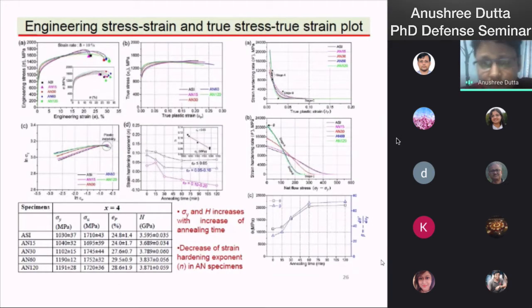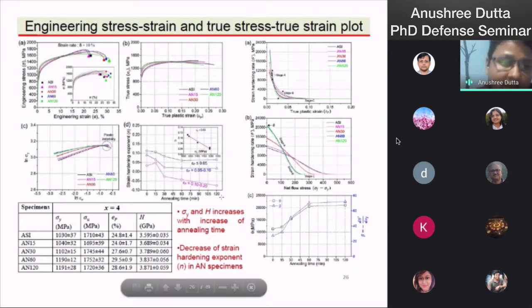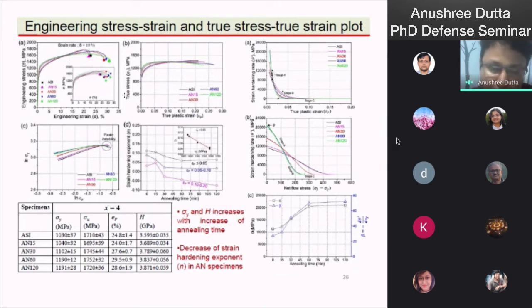The engineering stress strain plot shows that the annealed sample exhibited improved yield strength after annealing, and the true stress strain diagram shows the improvement of strength after annealing. The true stress strain diagram is plotted in log scale to estimate the strain hardening exponent, and the strain hardening exponent at different plastic strain is plotted here. And we can observe that the strain hardening exponent decreases with annealing time, and strain hardening rate is improved after annealing due to the interaction of the precipitates with the dislocation and the formation of Orowan loops.